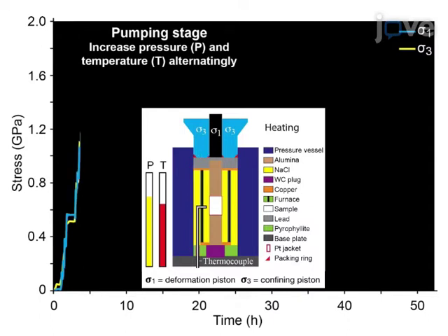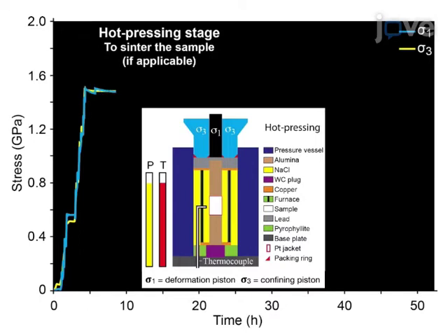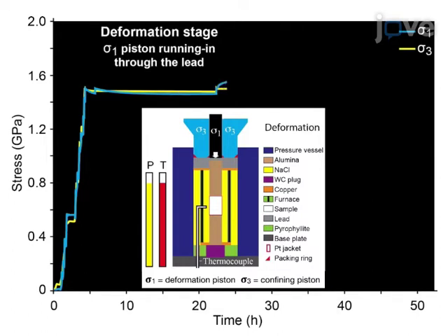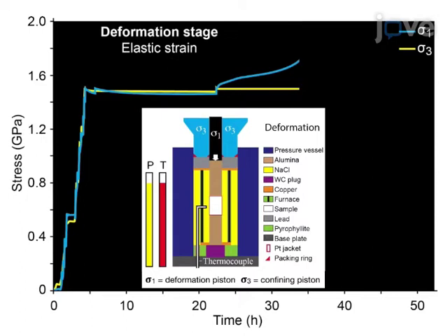pressurize the sample assembly. When the target pressure and temperature are achieved, a period of hot pressing is applied to sinter the sample, if applicable. Then, the sigma-1 deformation piston is advanced, moving through the lead, and then pushing on the alumina piston to deform the sample. This describes a yield point followed by an elastic then plastic curve during the deformation stage.